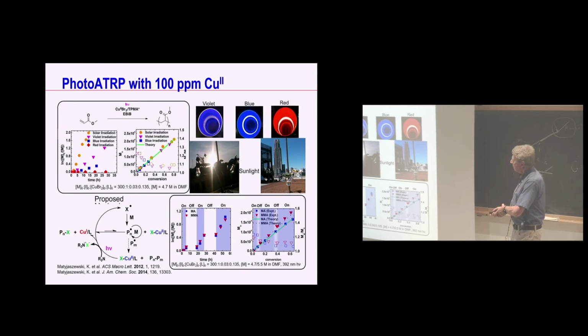For light, what you need is to excite copper-2 to an excited state species, and then you need an electron donor which can donate an electron in order to reduce copper-2 to copper-1 and produce activators. With red light, it doesn't work because copper complexes do not absorb efficiently at these wavelengths. But with blue you could see it faster, with violet even faster. If you do it on a sunny day, like at Cargese today, it would be a very fast reaction because you have a lot of sun. This is the rooftop of Mellon Institute on a sunny day. You could see that this was really on-off, on-off, on-off, and molecular weights were nicely controlled with low polydispersity.